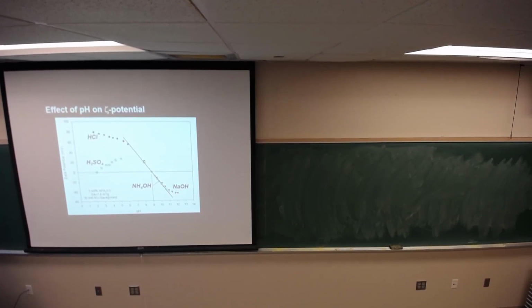If I add sodium hydroxide, the sodium ion that comes in with the NaOH does not significantly change the overall ionic strength. Because what will happen is that if you bring in HCl, for example, it turns out that HCl is not an indifferent electrolyte. Not only is it a pH determining ion with the H, but the chloride is not inert in that situation because you don't have a cation to convert to. So you use a background electrolyte. Just so that's a point of information.